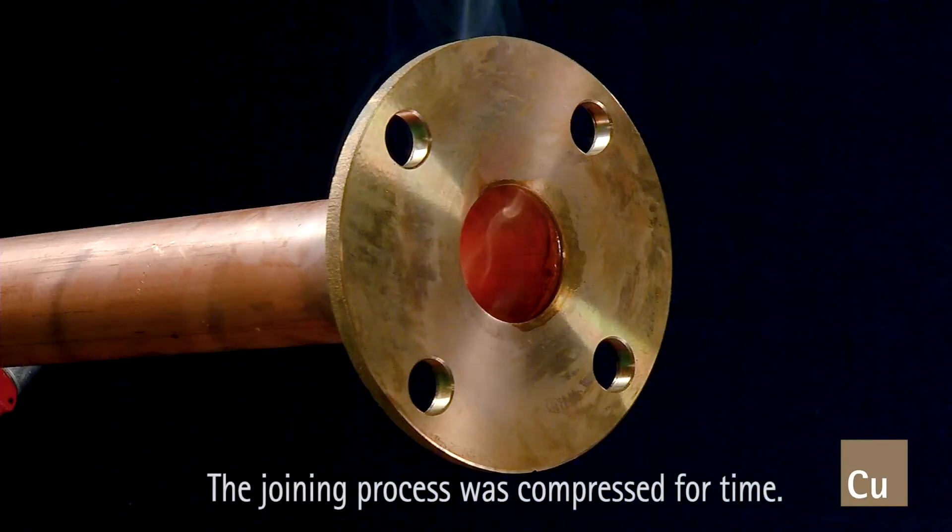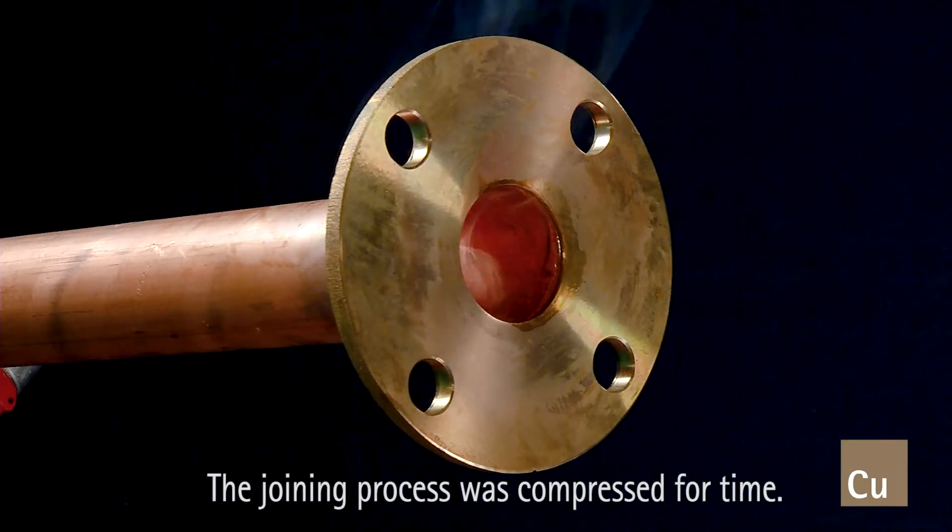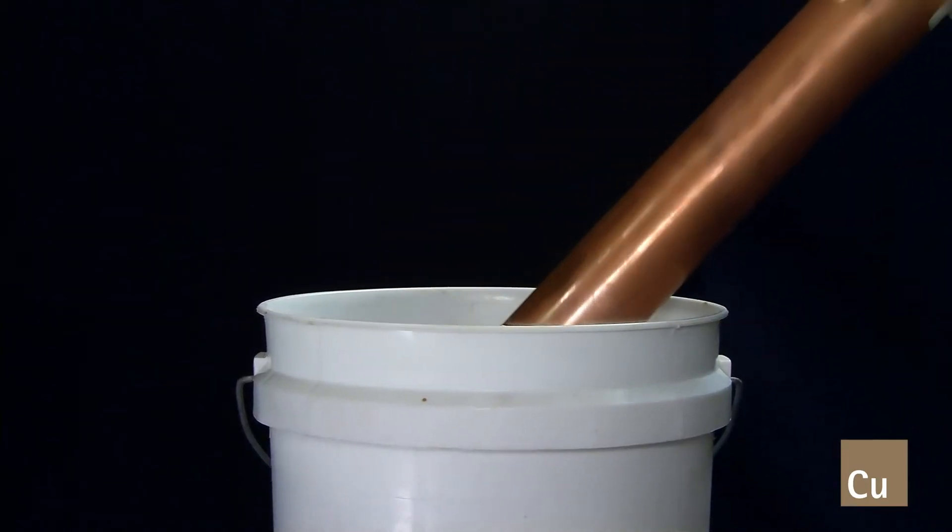When finished, allow it to cool to the touch. Shock cooling or quenching may cause rapid shrinking of the cast flange that could contribute to cracking of the solder alloy or the flange itself.